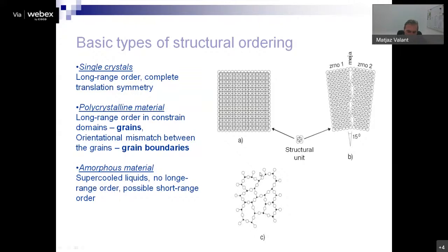schematic system here. It's an amorphous system. There's no translational symmetry, because the patterns do not repeat, but around each black circle we have 3 white circles, and around each white circle we have 2 black circles. So there is some ordering, and we call that short range order. This is typical for silicate glasses, for instance quartz glasses, or as I said, some liquid metals and similar.